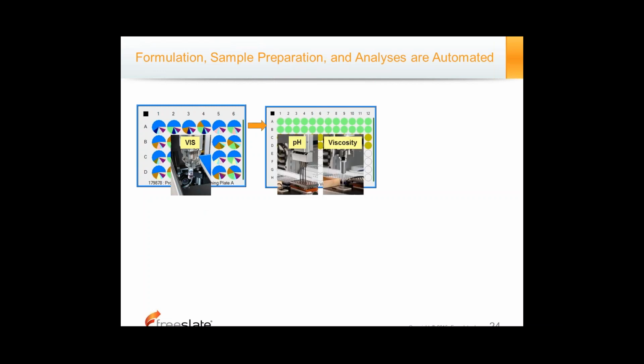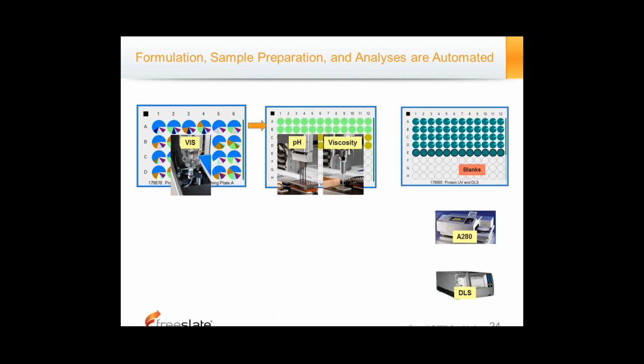The deep well plate is then subjected to viscometry. In this case, we actually use a microcapillary system, which can be complementary to the DLS viscosity measurements that Dan had just spoken about. And now we can also perform pH measurements in high throughput mode using a 4-tip pH probe. This is a solid-state pH probe, and there's an automated washing and drying protocol for that. So all 3 of these are techniques that are high throughput and unique to the BFS system.